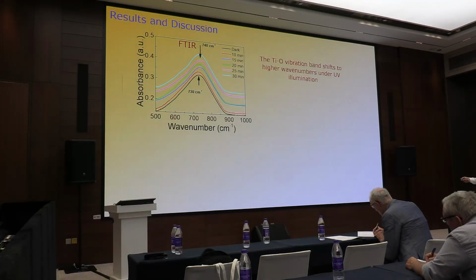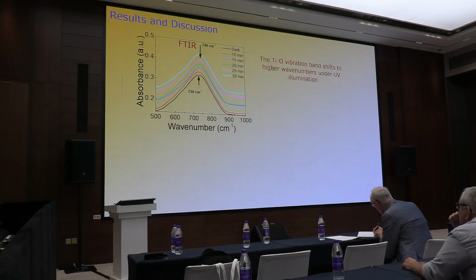Also, here you can see the FTIR, the vibration of this band. This band is the titanium-oxygen vibration band, and this band is shifted to higher wave number when we illuminate it with UV. It's a little bit, no? You have this shift from 730 to 740, only 10 cm^-1.